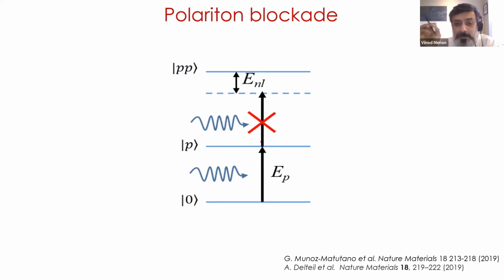If I do the calculation in not the Jaynes-Cummings model, but what is called the Tavis-Cummings model, where you incorporate the interactions of the particles, then you will see that as I go to the second polariton, two polariton state, because of the interactions, the energy level associated with this two polariton state is different from the energy level associated with one polariton. In other words, if I have two polaritons in the system, the energy spacing between the upper and lower polaritons is different compared to what it was if you had one polariton.